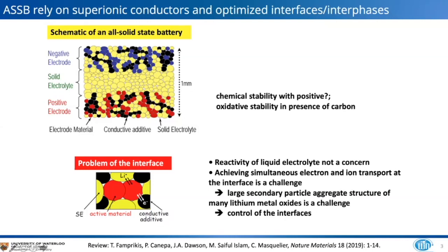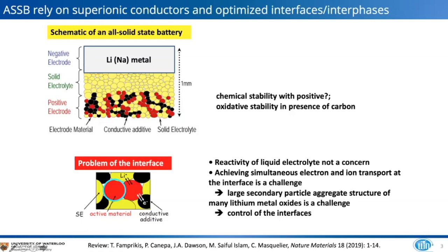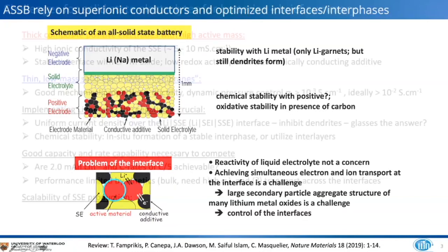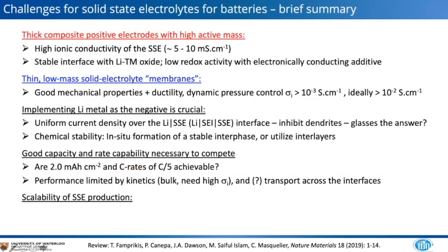More specifically, there are also issues of chemical stability of the electrolyte with the positive electrode. There's oxidative stability issues of the electrolyte in the presence of carbon. And ultimately, one really wants to use lithium or sodium. If one is using a sodium solid-state battery, one wants to use a metal anode. And this presents its own problems because, of course, many electrolytes are not stable with lithium metal. Really, only garnets are shown to be stable, and still dendrites will form. And so that usually requires the incorporation of some sort of protective interface. Those concepts are summarized in this slide with just a little bit more detail on the challenges.